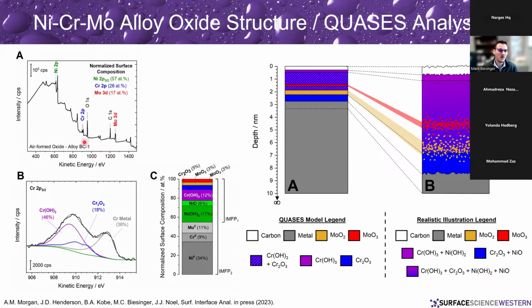So as a photoelectron is emitted, say an oxygen 1s photoelectron is emitted, it will come out with a kinetic energy of 890 or 900 and something. But if it comes from down here in this layer, it's got to go through all this layer to get out. And sometimes it doesn't make it. It bounces off and loses some energy, and so that's energy loss. And you can see these as you go up in binding energy of this spectrum, you get a larger and larger background. And so that's loss that's going on. So there's a lot of background electrons that have lost energy that's in here. And so by analyzing that, you can figure out layering and figure out the depth of where these photoelectrons are coming from.